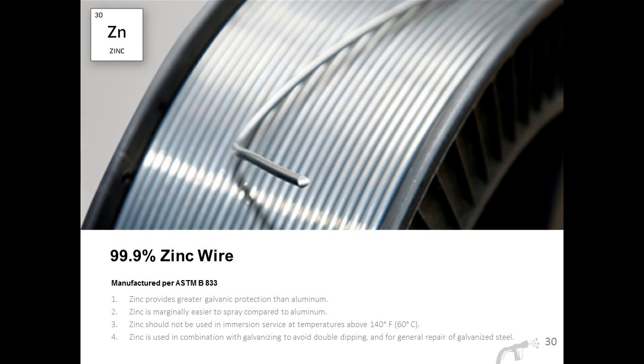Now, when we talk about specific consumables for metallizing in the bridge industry, we'll start with zinc wires. So 99.9% zinc wire manufactured per ASTM B833. If you remember from the beginning of the presentation, zinc provides galvanic protection, and it actually provides a bit more galvanic protection than aluminum. Its greater galvanic power protects gaps in the coating better than pure aluminum, and it's marginally easier to spray pure zinc than it is pure aluminum, and this is something we found in our own experience. Zinc tends to be easier to spray, and it certainly seems to be easier on our equipment. I would say aluminum kind of beats up our equipment, and as we go along, we'll address pricing too. But zinc wire seems to be a bit more of an affordable option.